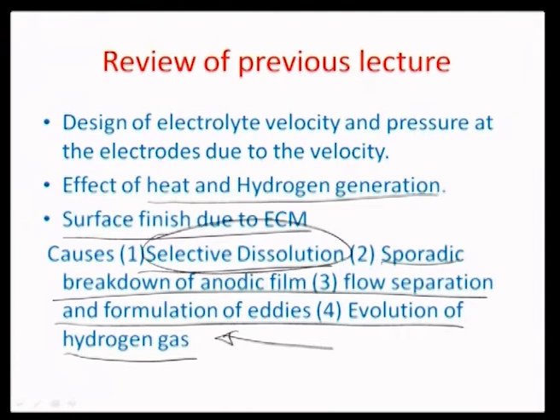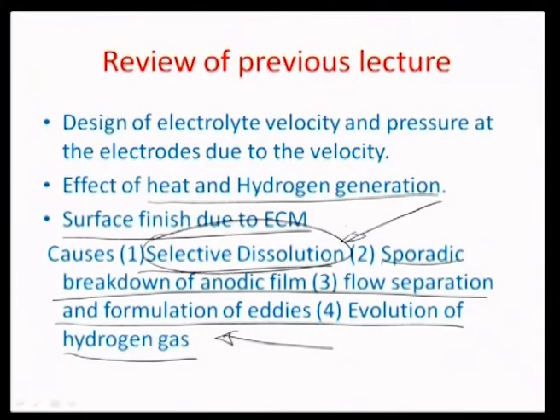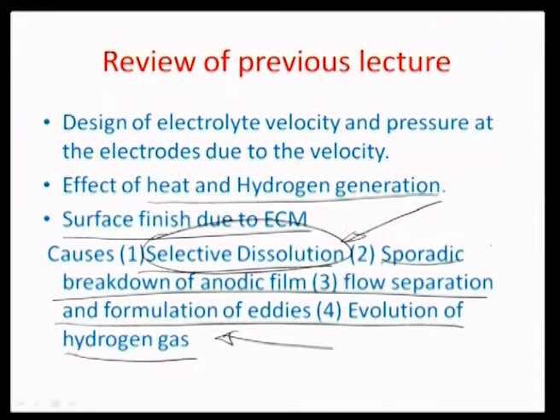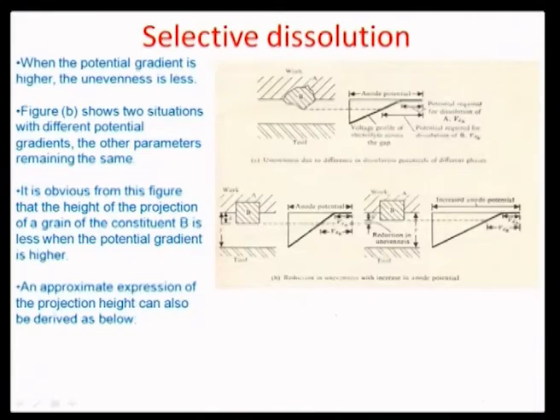We had already seen how two phases in an alloy A and B with different dissolution potentials would have a self-roughening effect, as opposed to the general self-leveling effect of an ECM process, because the potential of one phase may be slightly higher over the potential of the other. It was a very interesting case where roughness automatically gets generated because of difference in dissolution potentials of the two phases. Next we will evaluate the sporadic breakdown of the anodic film, after a brief recap of selective dissolution.